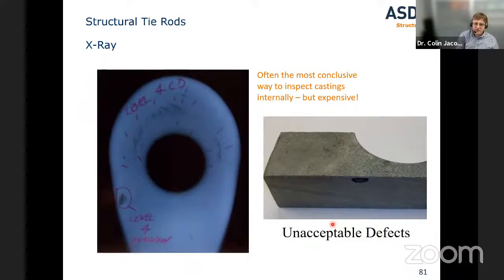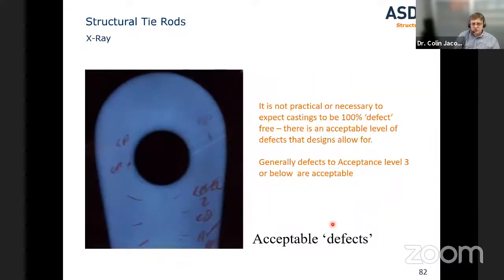Quite expensive X-rays, but they do highlight very visually any defects you may get. But I should note here that not all defects are unacceptable. It's impossible, really, to get a casting and not expect some defects. There are some very good codes out there, like the ASTMs and the Eurocode, which qualify what these defect levels are. And an experienced radiographer will be able to tell you what level the defects are. But typically, anything at level 3 or below is an acceptable defect, an acceptable risk for a casting.